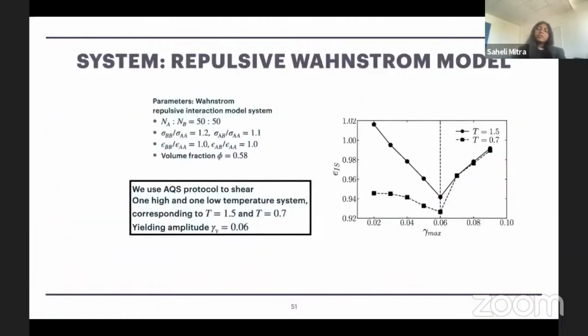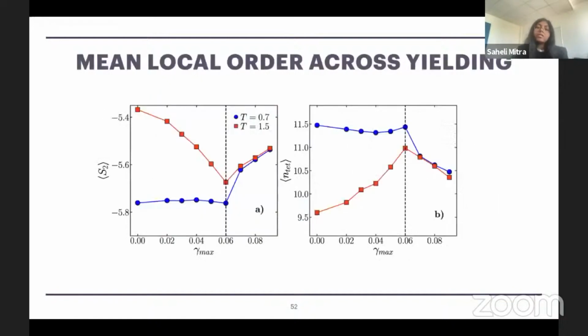So now we want to relate the structural order to dynamic heterogeneity, that is, to the plastic rearrangements in the system. For that, we start with the bidisperse model of glass forming, the Wahnström model, which interacts through the repulsive part of the Lennard-Jones interaction. For this model, the yielding amplitude is close to 0.06. We first compute the mean local order of S2 and Ntet across the yielding amplitude.